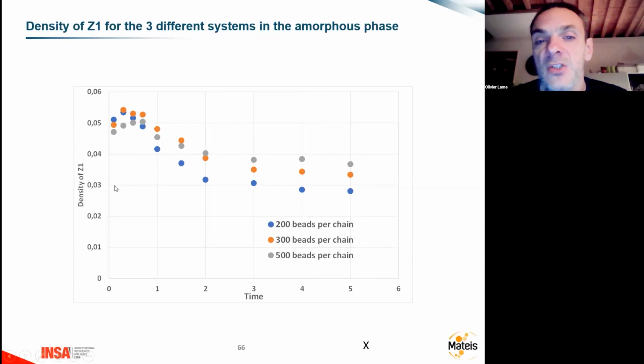But the decrease is for the reason we have explained before: we have a lot of very little chains in the amorphous phase, so they relax and disentangle. It's an important result because it's likely that when we decrease the density of entanglement, we weaken the amorphous phase. In this case, it seems that this is also a very important cause for the weak mechanical properties we have seen. The second thing we show here is that for 500 beads, the decrease is much lower, which is normal and expected, because the viscosity is higher and the possibility for the long chains to entangle is much higher.